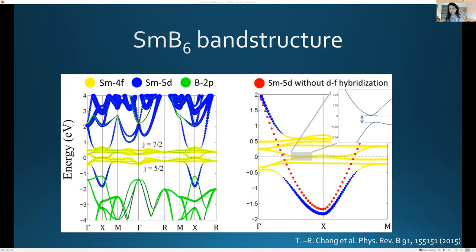However, because this is actually a Kondo insulator, the way one gets insulating behavior in this material is that these localized f bands in yellow here are hybridized with the d band, which is in red here, to give the hybridized blue bands, which you can see have a separation from the Fermi energy. And as a result, one does not expect any Fermi surface or any intersection of the Fermi energy with the band structure. Instead, one expects a finite gap, insulating behavior, and the absence of a Fermi surface.